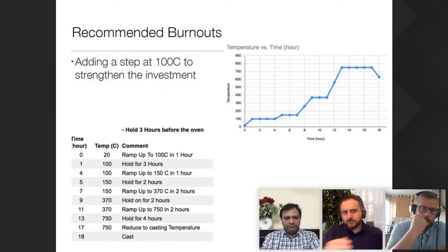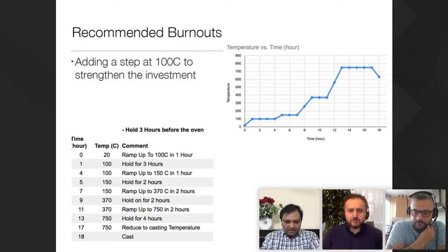I have another recommendation here - I think some of your customers may use this as well. We leave it 3 hours outside, we put it in the oven, but we don't go to 150 degrees or 200 degrees. We leave it at 100 degrees for 3 hours. We do that because we want to remove all the humidity.